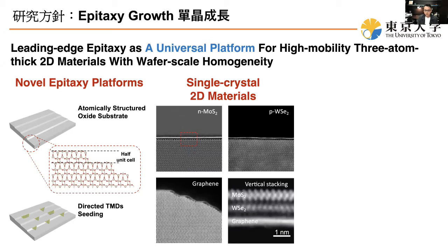Or, most recently, we found that we are able to create these materials in stacks. For example, first putting graphene, and we can directly grow tungsten selenide and molybdenum disulfide on top of these graphene layers. So immediately you have an atomic stacking of functional devices. This is a vertical p-n junction device being built over here.